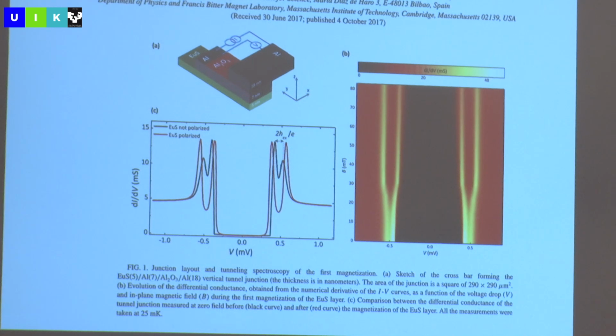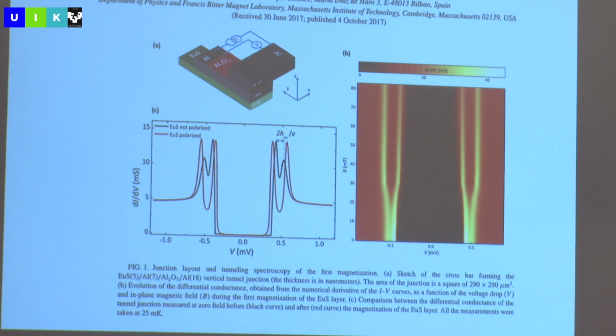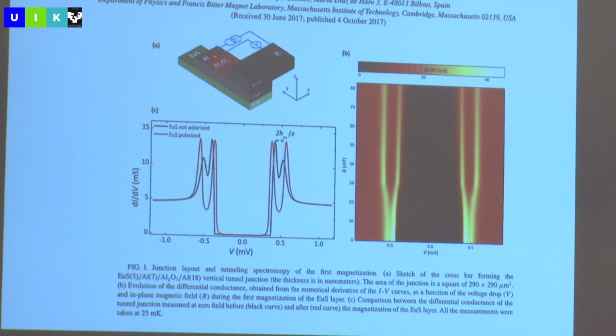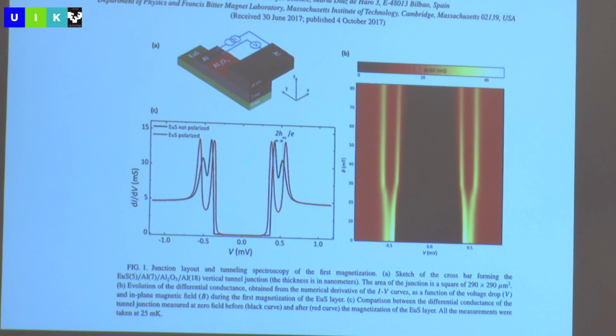So you see that the legacy of Tedrow and Meservey from MIT from the 1960s, 70s, 80s is now carried forward by Jagadeesh Moodera. These are experiments in Francesco Giazzotto's group, where as a function of the external magnetic field, you see this splitting of the density of states. This is a tunneling experiment in which one aluminum is just a tunneling contact, and the other aluminum is sitting against europium. In this case, now they've switched from europium oxide to europium sulfide, another ferromagnetic insulator. And the splitting of the density of states is here in this aluminum. This is just a tunnel, and they're tunnel injecting from that untouched piece of aluminum. So if you like that subject, you can do it.